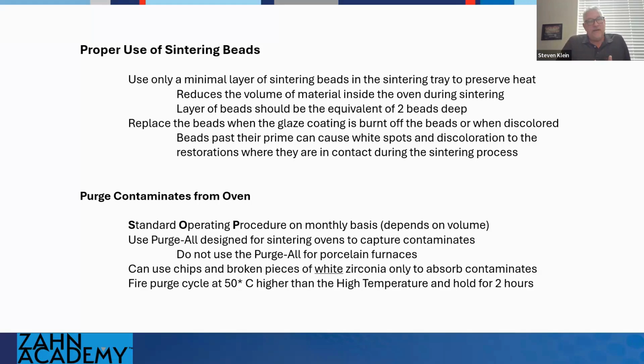One of the things too, when to replace the beads: you'll see either there's a glaze on those beads that has started to come off, you're going to see very dry, dull patch areas on those beads, or you're going to see them completely discolored, starting to turn that yellowish green, brownish color. That's time, chuck them and start over with a fresh batch. That is absolutely going to affect the shades of the restorations going in.